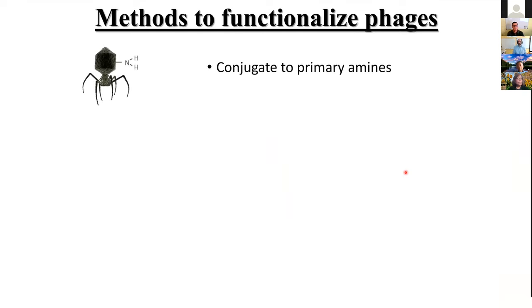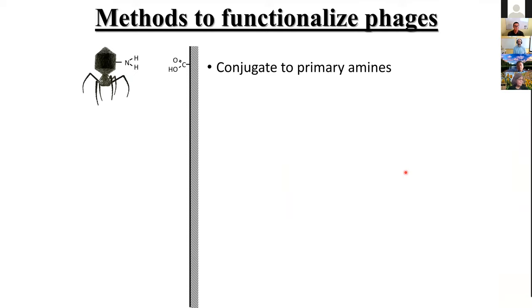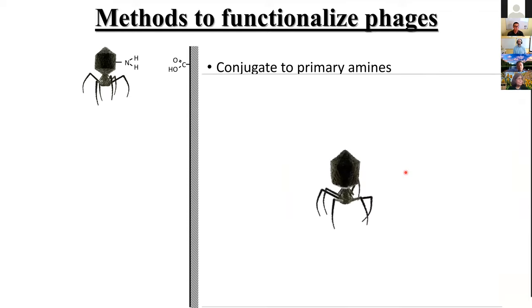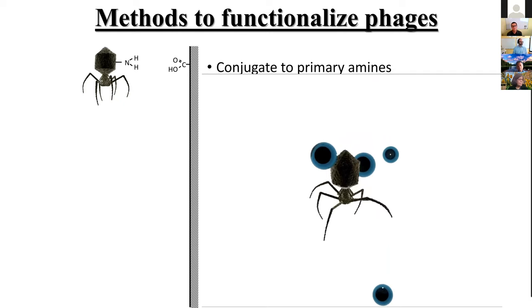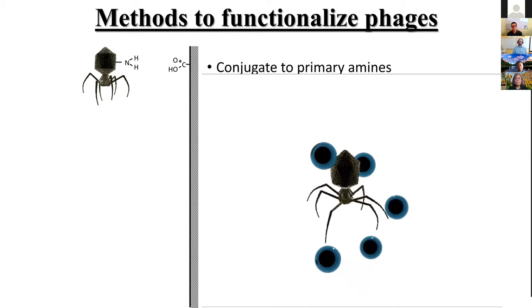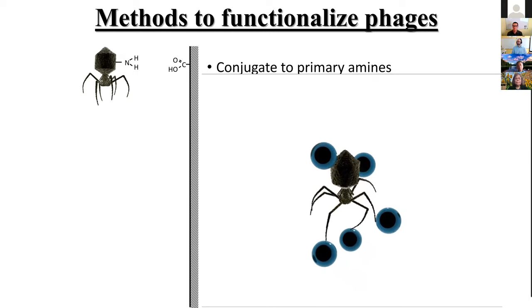How do we get bacteriophages onto magnetic particles? Traditionally, people have tried using primary amines, so just using, say, EDC, NHS-type chemistry, where we would just bind onto a surface that's got a carboxylic acid. This is a little bit of a problem. The whole phage is made out of proteins on its capsid. So we would want particles to bind here, but since the whole phage is made out of proteins, including the tail fibers, which recognize the bacteria, they would bind there too. And this would result in a phage that can no longer infect bacteria.